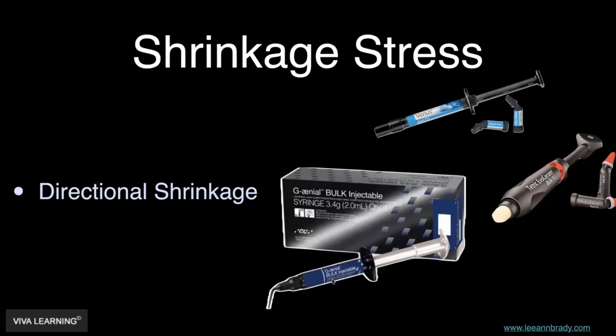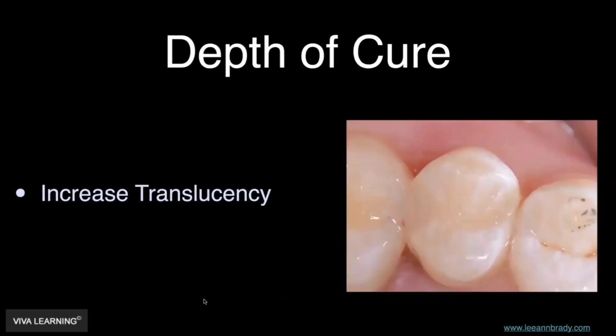And so I don't know how they figured this out, but they figured it out. They can control the direction in which the polymerization shrinkage is occurring, and it doesn't all occur in one direction, it's multi-directional. And therefore, the stress that's accumulating on the marginal interface actually decreases to the point where it's no longer a concern to polymerize a bolus that's 4, 5, 6 millimeters thick, and you're not going to have to worry about it degrading that bond.